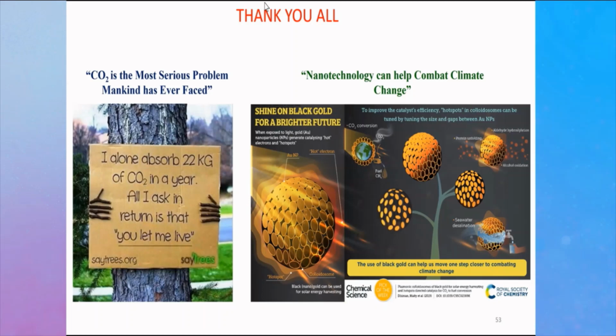Kishore Kampra, why only gold particles? The simple answer is because gold has a plasmonic behavior, it shows surface plasmon in the visible light. But you can also use silver, you can also use copper. But again, silver and copper have the tendency to oxidize and become oxides, no more plasmonic. So that's why gold is stable and active. That's why you use gold. Obviously, it has its own disadvantage in terms of its expensive nature.